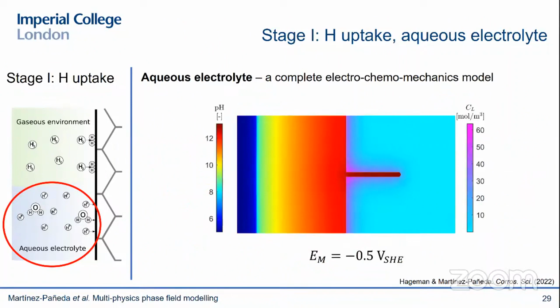And this is the kind of representative results that you get. So for a given environment, applied potential, you'll get a distribution of any relevant quantity in the electrolyte, in this case the pH, but it could be also the potential or any concentration of ionic species. And then in the metal, you can predict the absorption of hydrogen as a function of time. And you can predict this as a function of the material, the environment, the fluid velocity, the loading conditions, any scenario that you can think of.